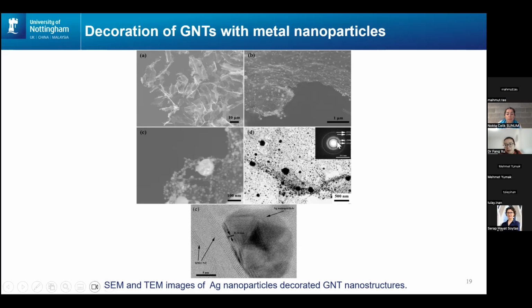Okay, and we have the diffraction pattern to confirm existence of silver, and the high resolution TEM showed the silver nanoparticle lattice as well.